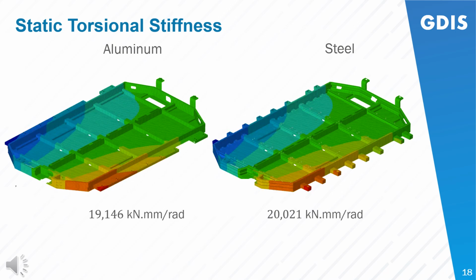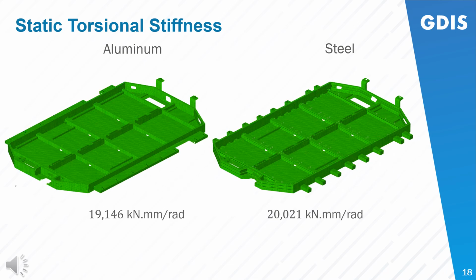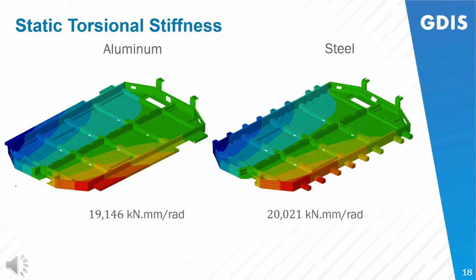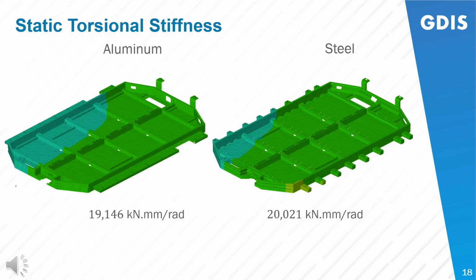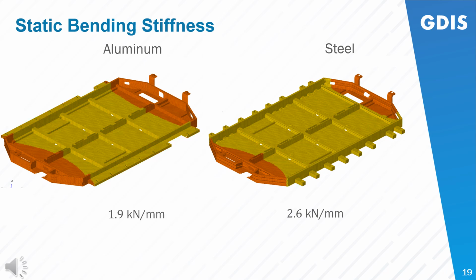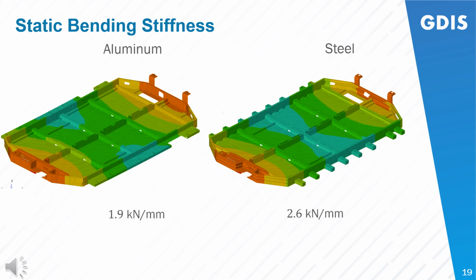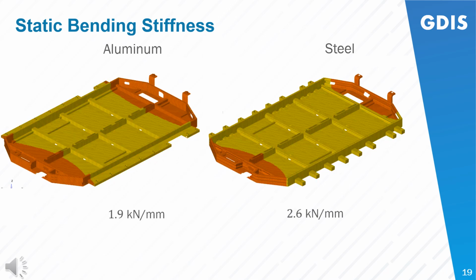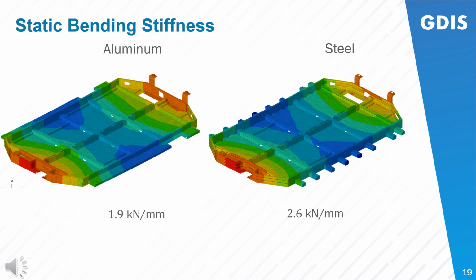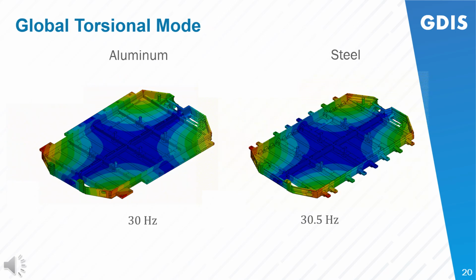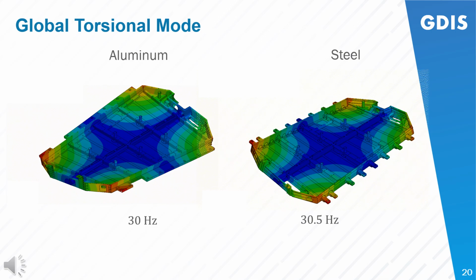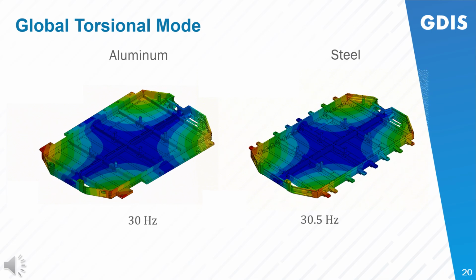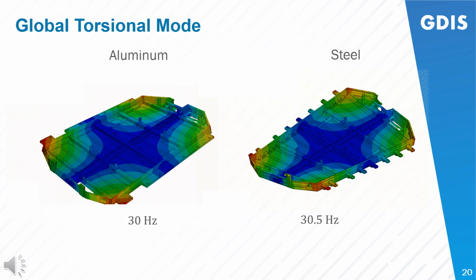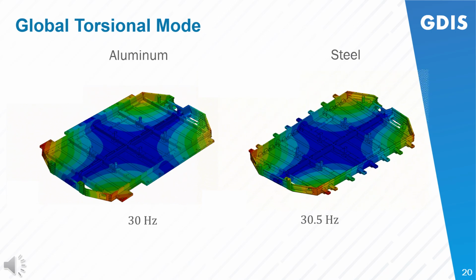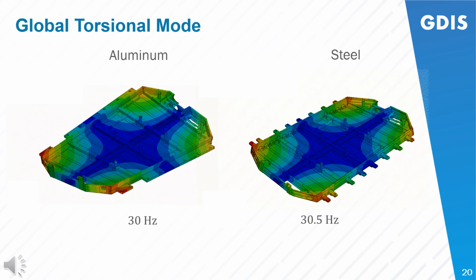Here you can see a comparison of the animations between the steel on the right-hand side and the aluminum on the left-hand side in static torsional stiffness. Similarly, here is a comparison of the mode shapes between the steel on the right-hand side and the aluminum on the left-hand side in static bending stiffness. And here is a comparison of the global torsional mode between both the steel and the aluminum. We note that they're fairly similar in behavior.